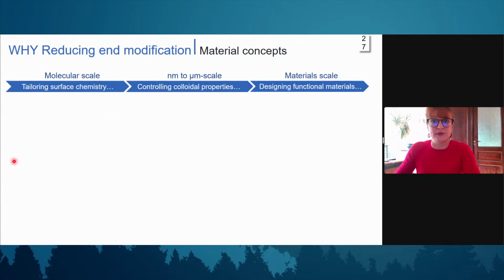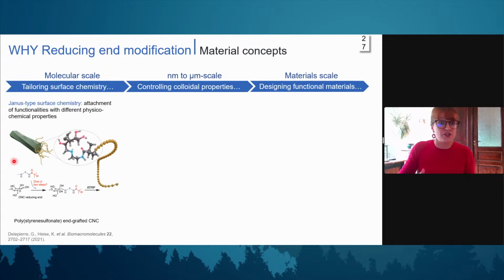Nevertheless, from the material side, it's really interesting because controlling the surface chemistry at the molecular scale leads to controlling colloidal properties in the nanometer scale and also micrometer scale, and then finally to the design of functional materials with nanometer anisotropicity due to the spatial selective modification. So in terms of molecular scale controlling or tuning, we can, for example, as I mentioned before, synthesize these Janus type constructs. So we attach something to the reducing end with completely different physical-chemical properties. It's something that I've been working on together with Gwendoline Delepierre. We grafted polymers to the reducing end groups.